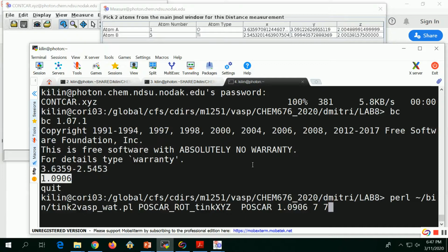and then the amount of vacuum along x and y, along z, y and z, which, if you take it a little bigger, will not change the results. Ideally, if you have unlimited numerical power on your cluster, you can put like 10 or 15 angstrom. But in VASP, vacuum costs something. The larger the amount of vacuum, the longer the calculation will be. And if your amount of vacuum is bigger than 7, maybe bigger than 8, you just repeat the same calculation with different amounts of vacuum, and results will converge. They will stop depending.